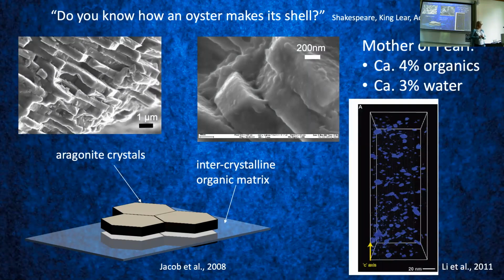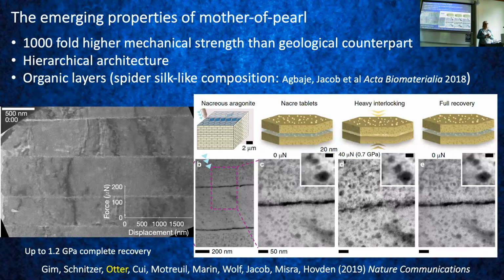And that's quite important for the mechanical properties of these aragonite tablets. But what also came out through work from other people is that these organic molecules actually guide the crystallization, and they shape the form of the crystal, or of the grain, while it's growing, and they also align the pieces so that they will become twins. How exactly that forms, and which groups are mechanistically involved, we don't know yet, but this is the job of these organics.